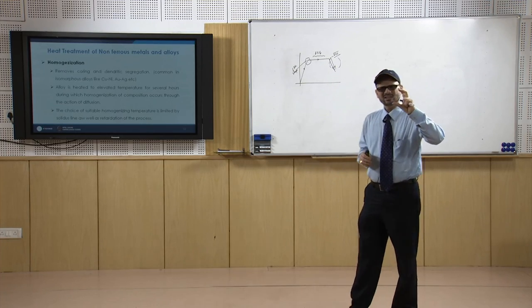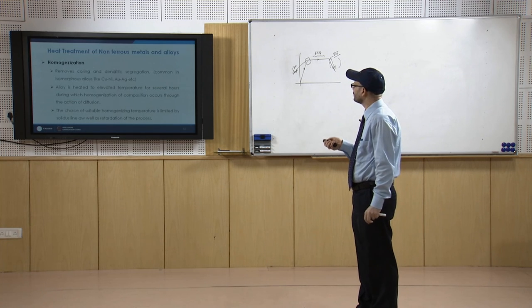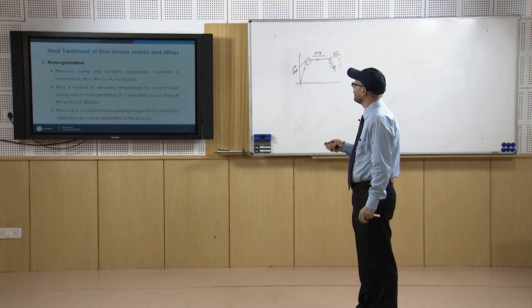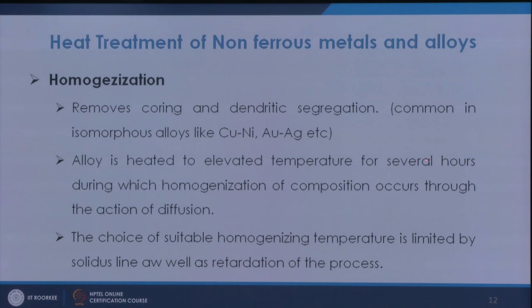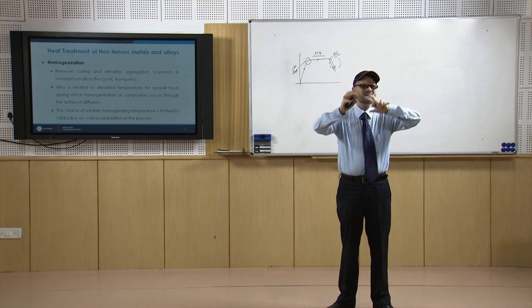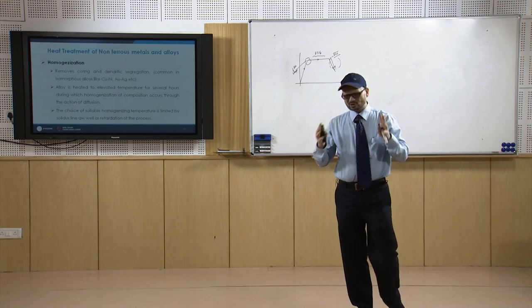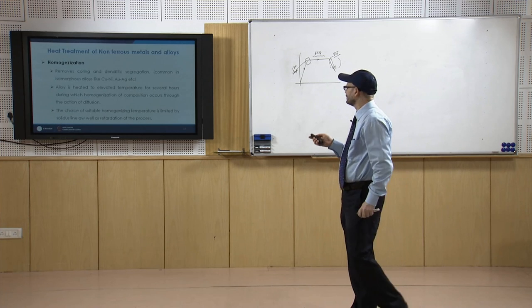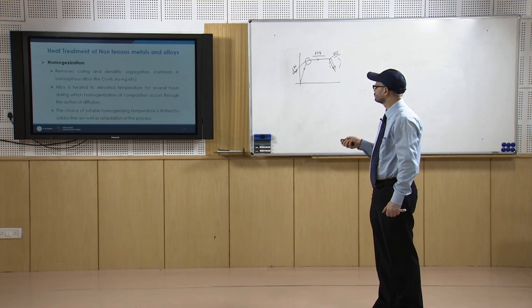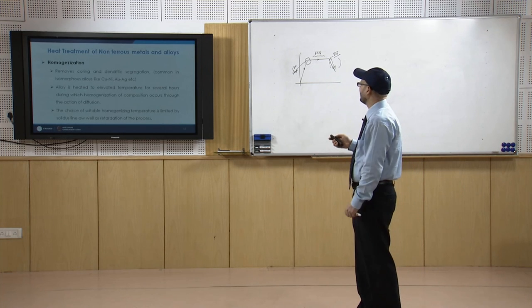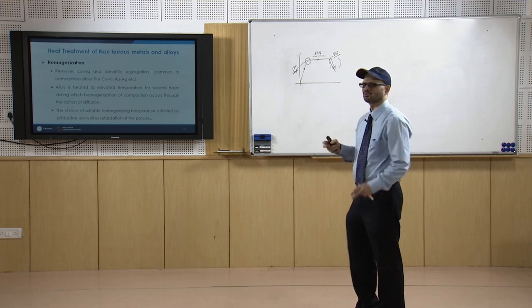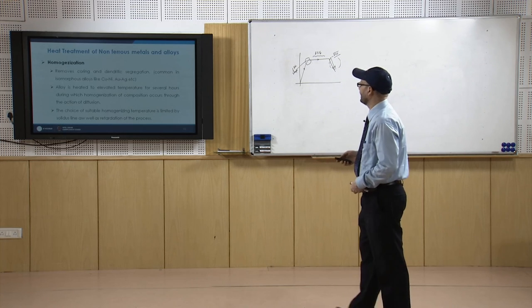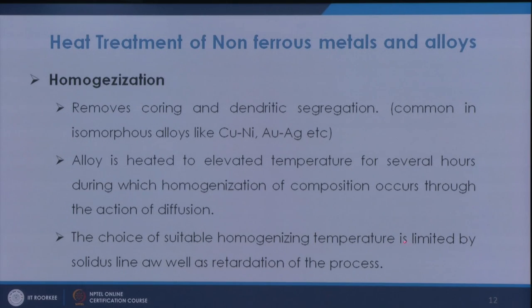So, that is removed by this homogenization process. In that, basically the alloy will be heated at elevated temperature for several hours. So, if you heat, then what happens? The composition becomes homogenized, and the composition becomes thoroughly the same, because of the action of diffusion, so it becomes homogeneous. And the choice of suitable homogenizing temperature is limited by the solidus line as well as retardation of the process.